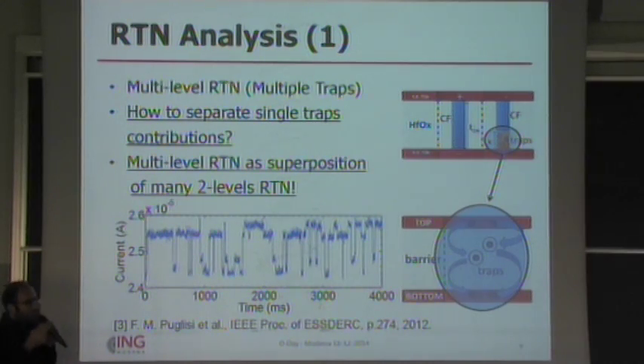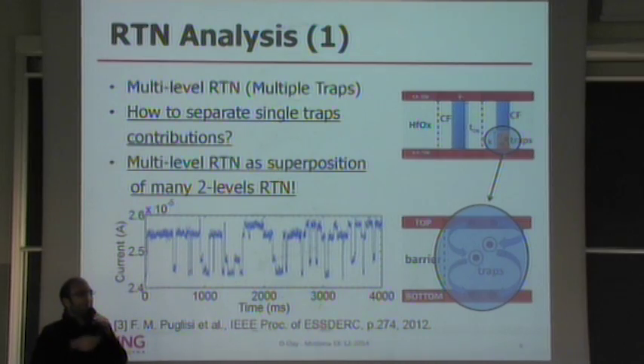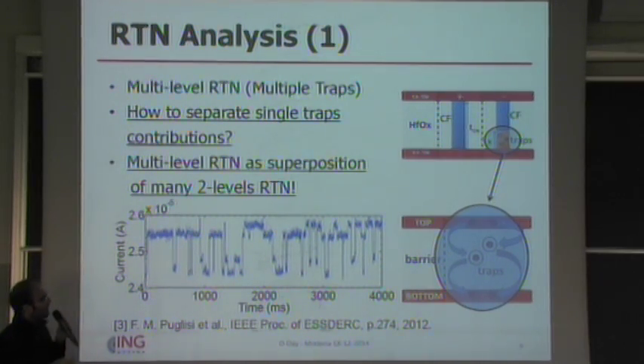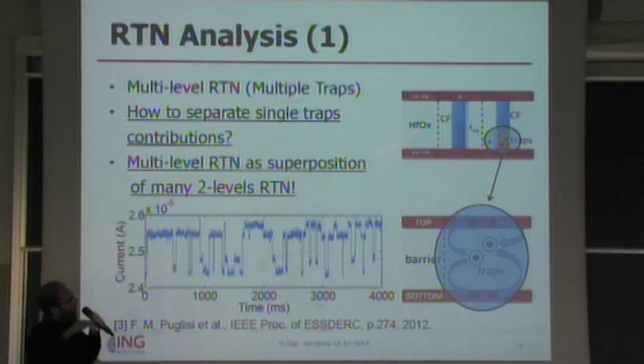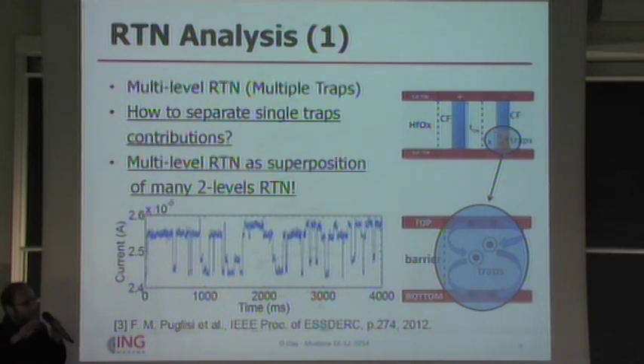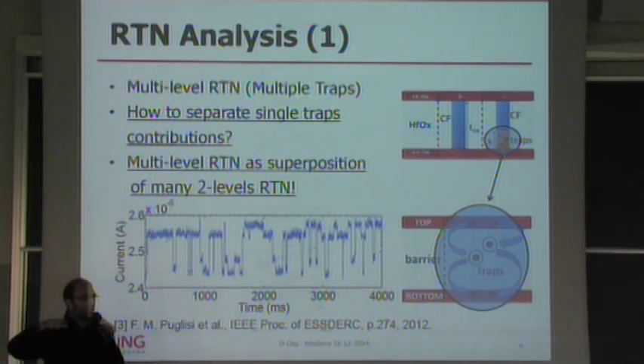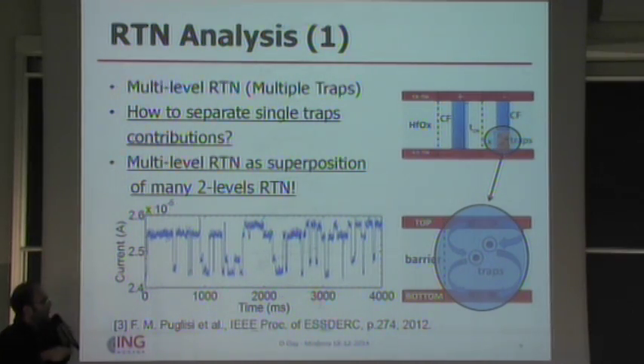And if we have 2 discrete levels, we refer to it as 2 levels RTN, and typically, from the literature, this is associated with some kind of trapping and detrapping activity at some defect sites in our device, for example, here in the barrier, but it's just an example. And a 2 levels fluctuation is associated to 1 defect. But we are dealing with multi-level RTN, so we argue that there are multiple traps in the device.